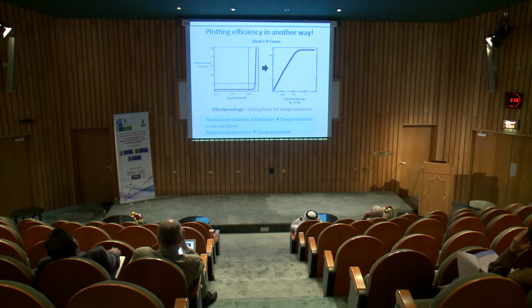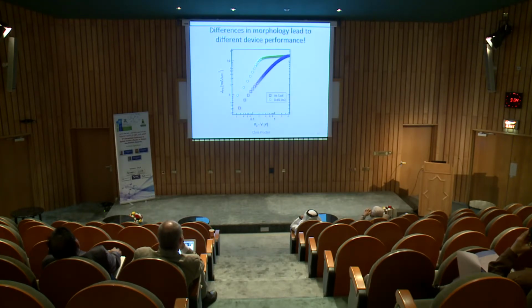So now, what does the plot tell you? If you look at how soon or how fast the photocurrent saturates at low bias, if you see the saturation in photocurrent, it means that the charge extraction is not a problem in the devices. And then if you look at the maximum photocurrent, it also gives you information about how efficiently your device generates charge. So now this is the actual photocurrent for our two devices.